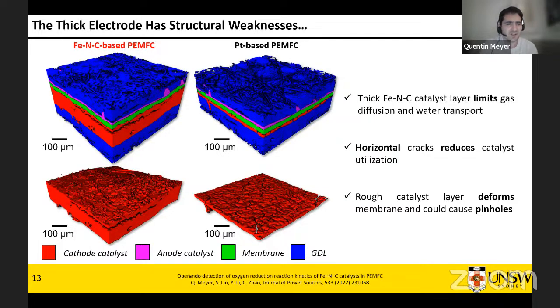And because your iron nitrogen carbon layer is very thick, it will limit gas diffusion and water transport. We can also see here a very visible crack in the thickness of the catalyst layer. That's typically what you want to avoid because right here there will be no electrical contact. It's a perfect area for water to accumulate, and gas diffusion may be challenging across this area. If you look on the other hand at platinum on carbon, it's pretty much an ideal case.